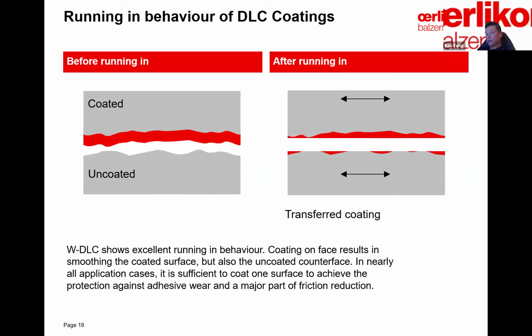I mentioned DLC has low friction and high wear resistance, but I'm not suggesting DLC will not wear. As a matter of fact, all materials wear, even diamond wears. But when most materials wear in engineering applications, they create debris particles. And if those debris particles are not flushed away from the contact interface by lubricants, they become wear particles and accelerate wear.